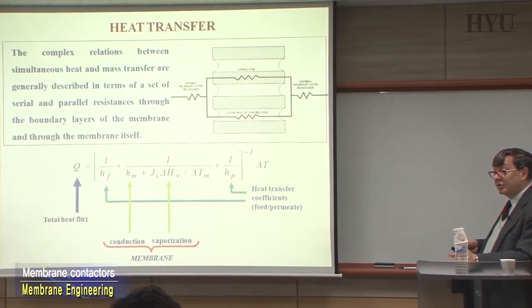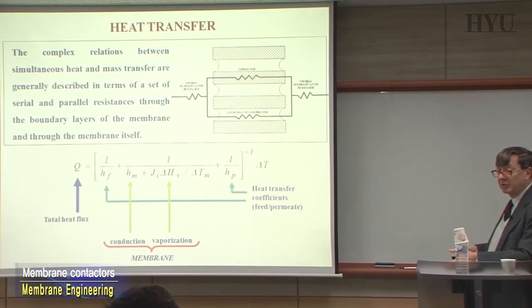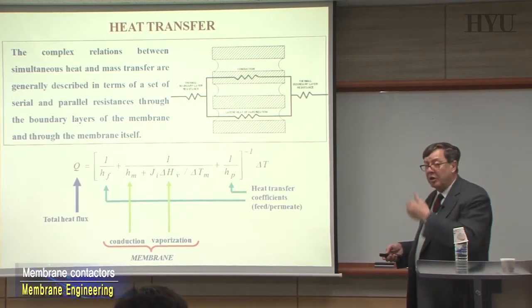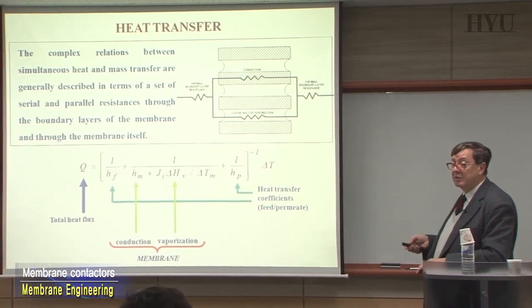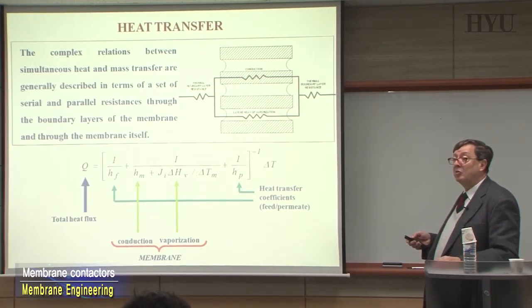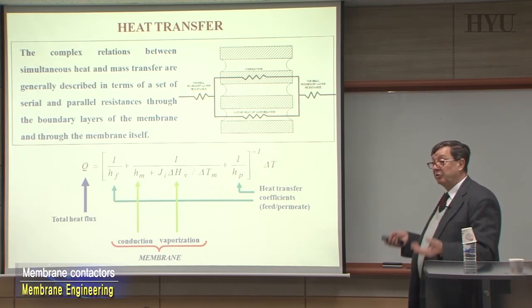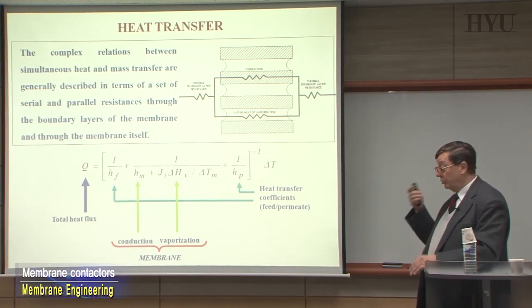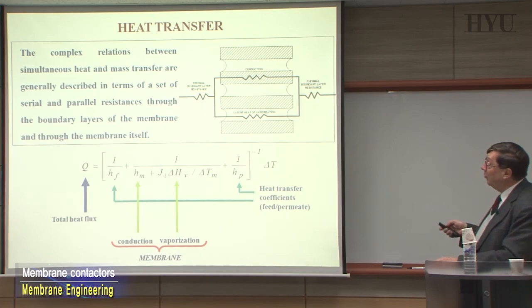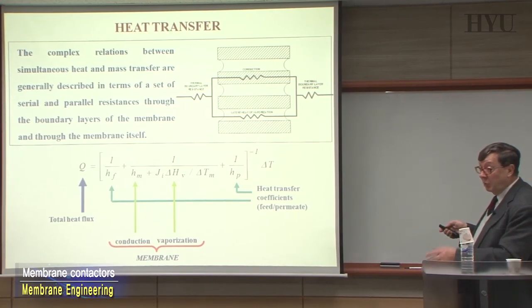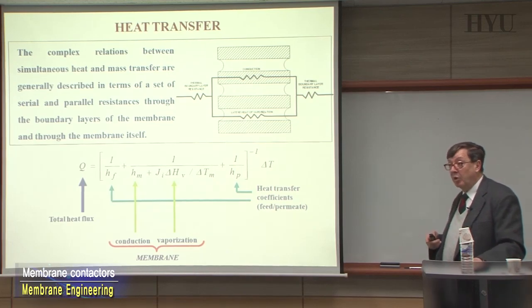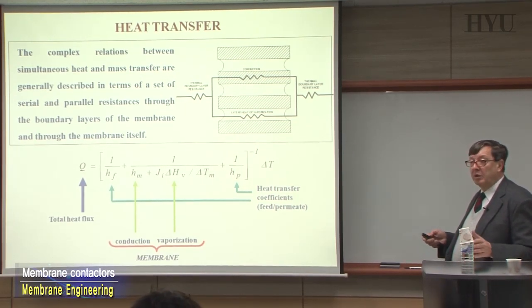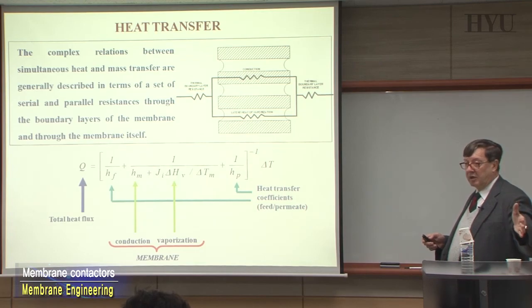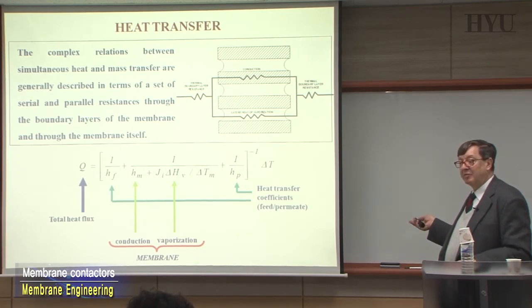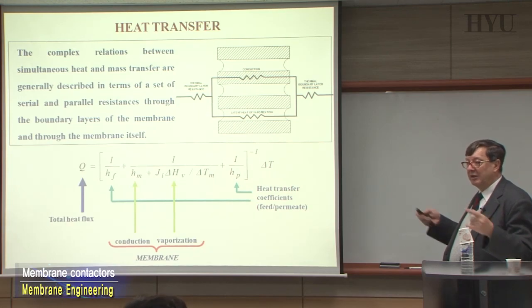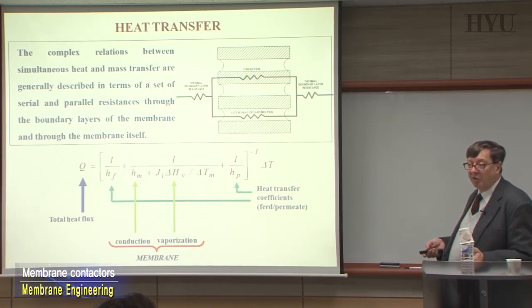All this, at the end of the story, is important, but not very important, because the change in the resistance that we have in the system at the interface, etc., does not affect too much the overall transmembrane flux. Concentration polarization is negligible. It means the concentration does not have a big effect. What is more important is the heat transfer, which is related. Until today, people work in this area trying to understand more. We always assume heat transfer and mass transfer totally independent. We don't put in any relationship because it becomes too complicated to solve the equations.